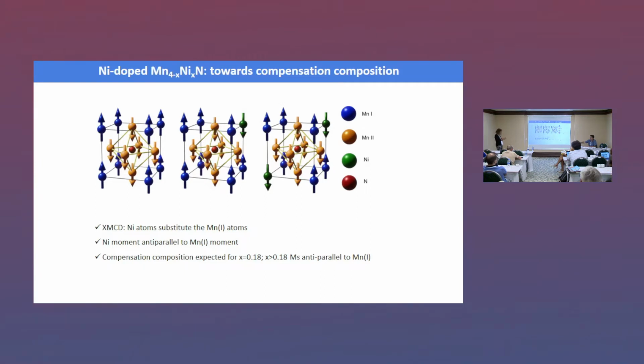Via XMCD measurements, they found out that the nickel was actually substituting the manganese one, on this corner side, and their magnetic moment was anti-parallel to that of the manganese. This means that by increasing the concentration of nickel, you can reduce the magnetization, which was expected based on what is known from neutron scattering measurements on bulk systems.